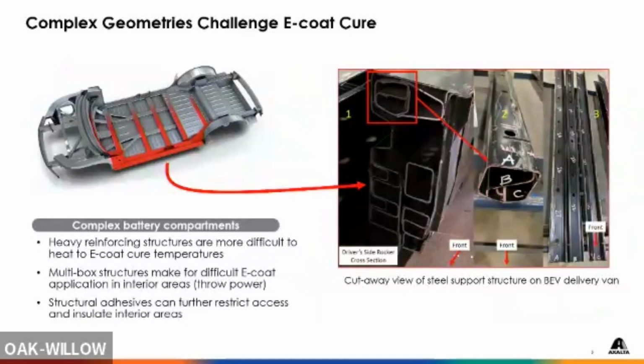So this is a cutaway of an EV van, and it demonstrates the complexity that I was referring to earlier. If we're looking at a traditional internal combustion engine, we're used to that frame. That frame is bent metal. It's hollow. We know how to coat that pretty easily. When we apply heat to it and bake it out, we know we can achieve cure. When we get to these EV models, now we're dealing with very complex, heavy heat sink areas that require additional heat to cure. So if I apply a 160 C coating to that, more than likely that interior area is not going to cure. And that's why we are now targeting 140 C.